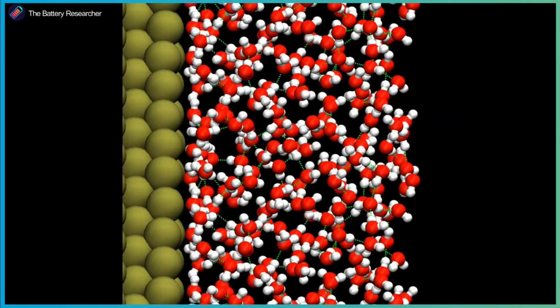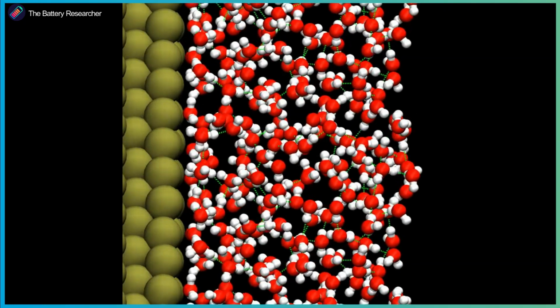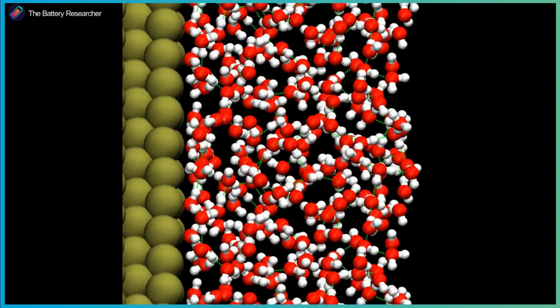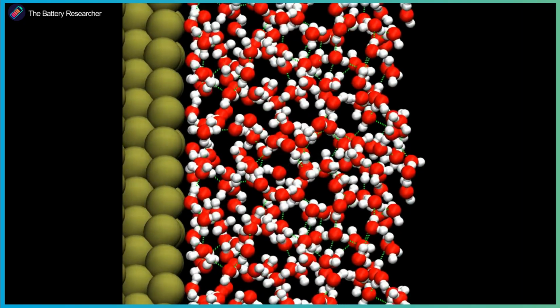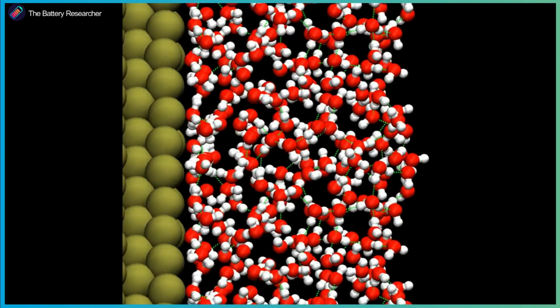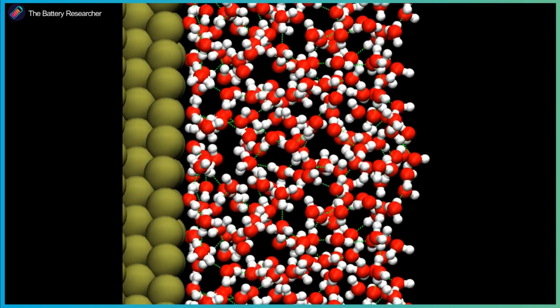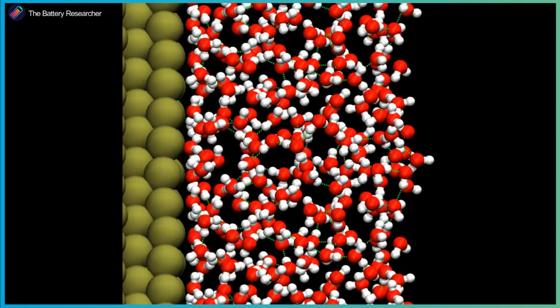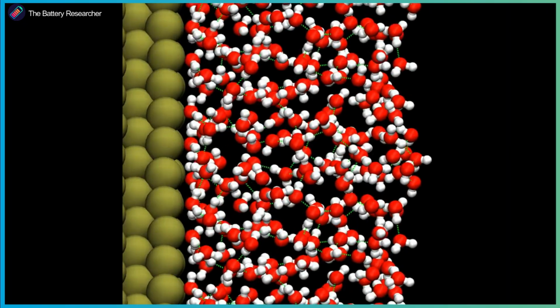And so we need a method that we can average. So we have to average over many, many different configurations. There are different ways that are very well known in chemistry and physics, but molecular dynamics is one specific method. So you just do a long movie. In principle, it's like a movie. You can watch it, you can see the atoms move, and then we do the appropriate averages. And this is well known. So molecular dynamics is well known. Ab initio is also well known. Ab initio means from first principles. This means these are quantum chemistry calculations where the only input are the positions and the elements themselves.